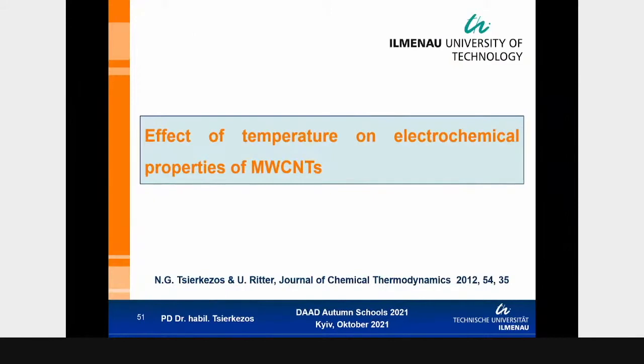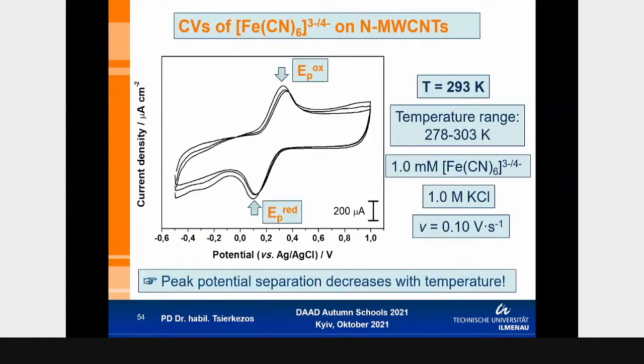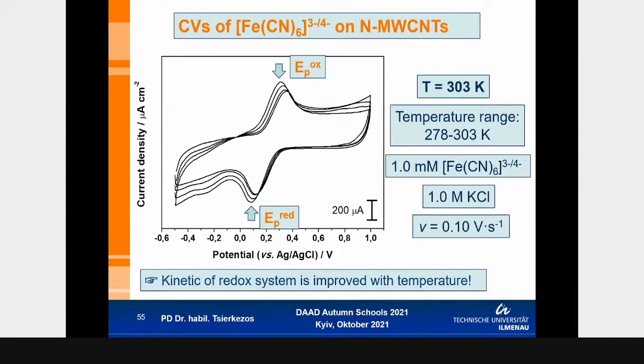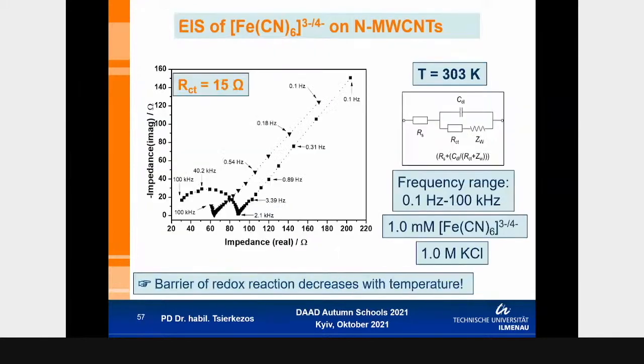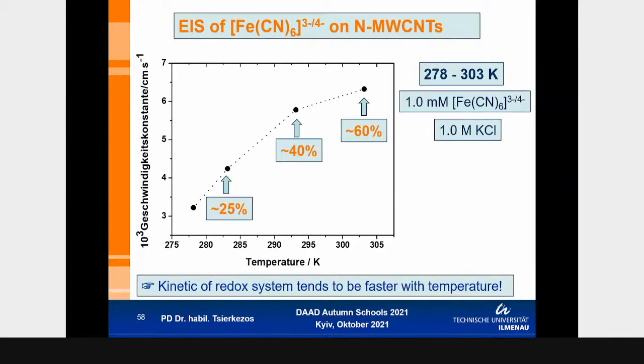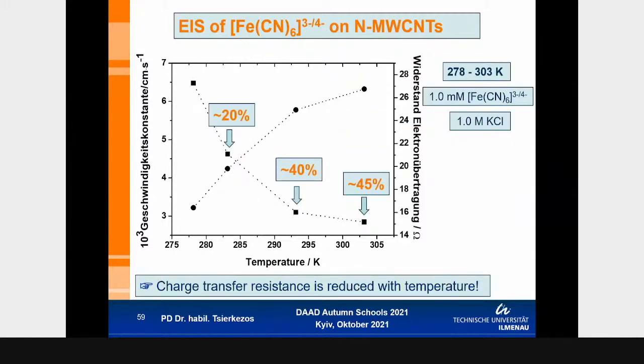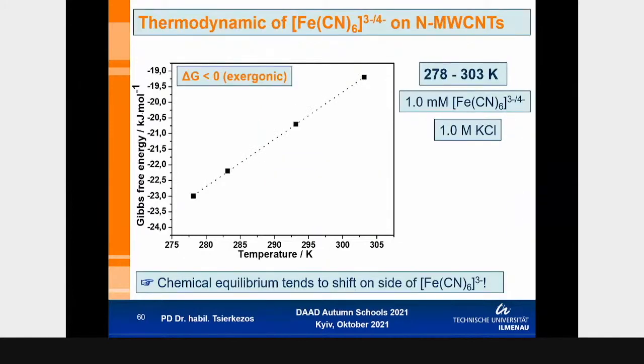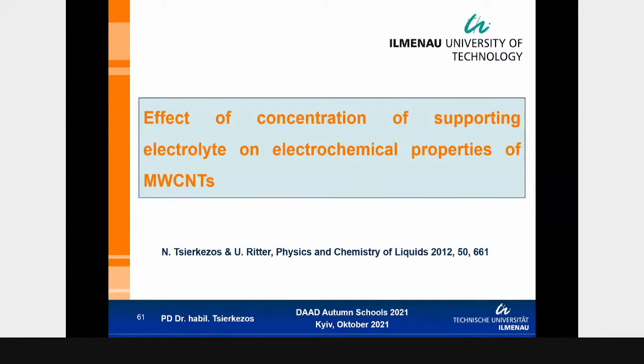A short investigation of the effect of the temperature has also been done. And we observe expectable results, that the kinetics is improved with the temperature, something that was expected. The same with impedance spectroscopy. We have an increase of about 60% of the kinetics of the redox system when we increase the temperature from 5 to 30 degrees. And the same, we have a decrease of about 45% of the barrier of the charge transfer resistance if we increase the temperature. Okay, and we also observe that upon increasing the temperature, the exergonic reaction shifts in the direction of the oxidized form of the redox system.